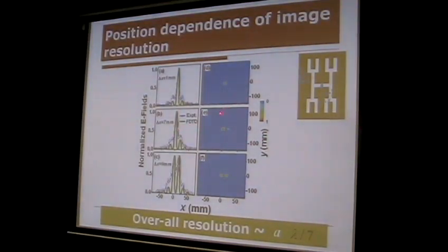Compared with the silver lens, a shortcoming of our structure is that it is not homogeneous along the lateral direction, so the image resolution must depend on where you put your source. So we measured 3 different situations, defined by the distance of the source from the center. For the situation very near the center, you find that it is clearly distinguished. For a relatively large deviation, you find that it's still distinguishable.